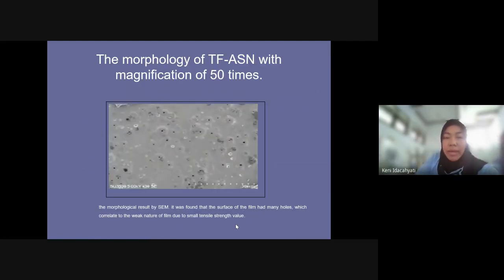The morphology of thin film astaxanthin with magnification of 50 times. The result, the morphological result by SEM, it was found that the surface of the thin film had many holes, which correlate to the weak nature of the film due to small tensile strength value.